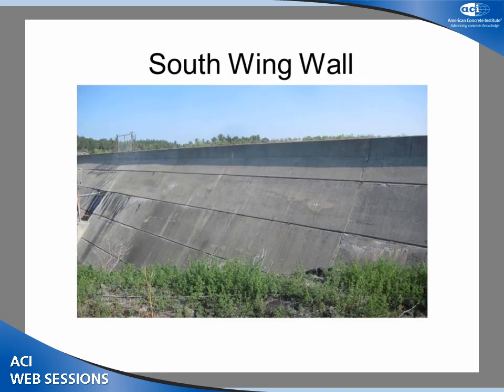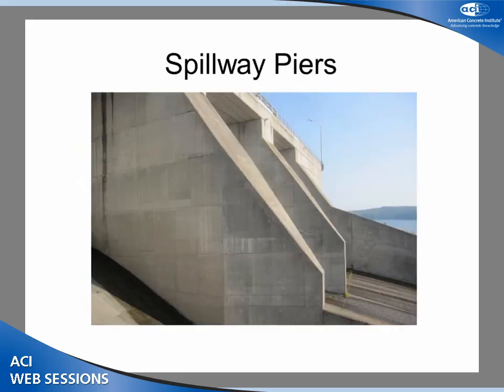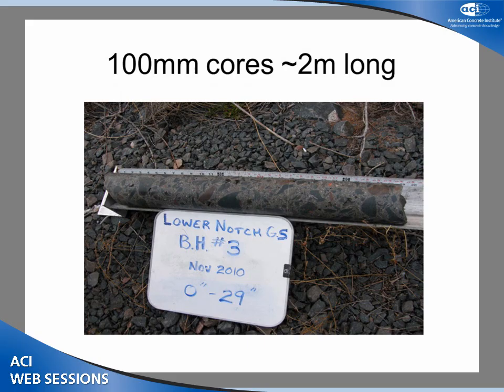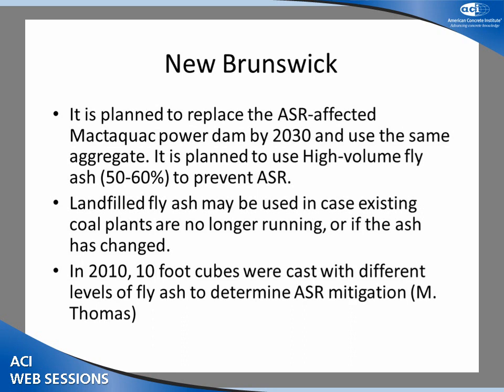This is on one of the wing wall sections. Again, there's no ASR damage. There's a bit of frost damage in a couple of places, but no evidence of ASR. We were down in the tunnels. We've taken cores. We've done damage rating indices. We're not seeing any evidence of damage with that structure. Yet there are structures built with similar aggregates in the neighborhood with Portland cement that have all cracked up. So we've got a good basis for that. So some of the cores we use for the damage rating index testing, we've got cores 6 feet into the structure to evaluate the performance.